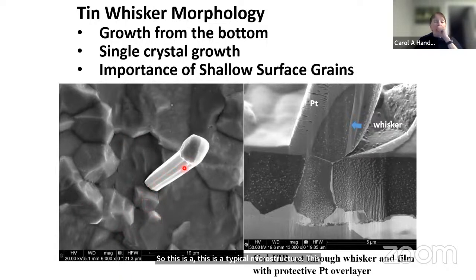It's on the order of probably 30 microns. In this particular one, because this is coming out at you, you're seeing more like the projection. So this is maybe 30 to 50 microns in length. This is the structure of where the grain boundary is in the film. This was the original free surface, the top surface of the grain, and you can see the oxide has ripped here. This was the oxide. This was the original grain, and the whisker formed. It forms by growth from the bottom.